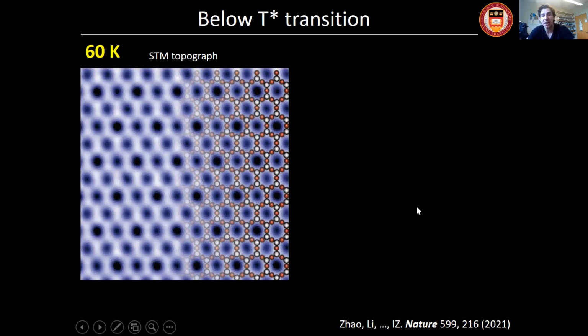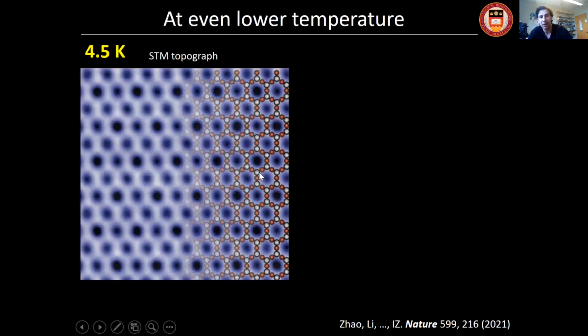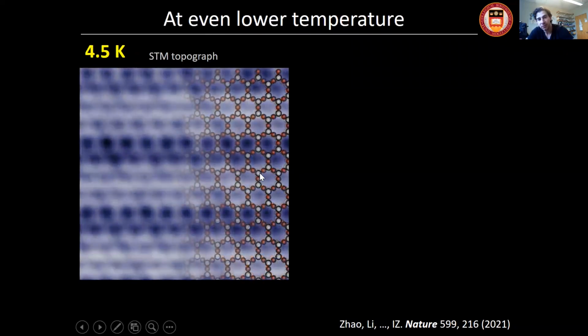But the interesting thing that we saw, and it took us a little while to really figure out what's going on, is if you cool down a little bit, all the way to 4 Kelvin, this topograph is going to turn into this. So you see this stripe modulation on top of the Kagome lattice in the background.